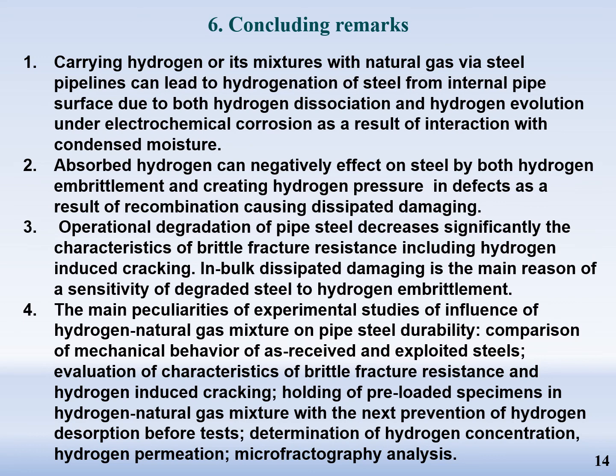And finally, some concluding remarks. Carrying hydrogen or its mixture with natural gas via steel pipelines can lead to hydrogenation of steel from the internal pipe surface due to both hydrogen dissociation and hydrogen evolution under electrochemical corrosion as a result of interaction with condensed moisture. Absorbed hydrogen can negatively affect steel by both hydrogen embrittlement and creation of hydrogen pressure defects as a result of recombination, causing dissipated damage.